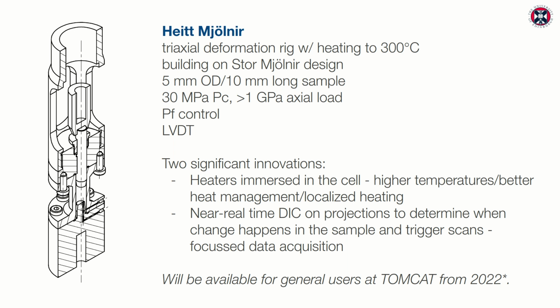So that's digital image correlation on projections, where we don't acquire data all the time, but we want to use DIC to determine when change is actually happening in a sample and only acquire data when it is really relevant. In that case, we hope that we can cut out a significant amount of that data overhead that really is more cumbersome than anything else. This cell, by the way, will also be available for general users at Tomcat in 2 years' time. So that is a deal that we struck with them.